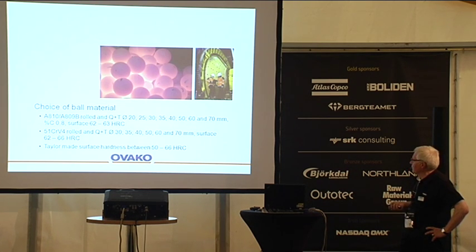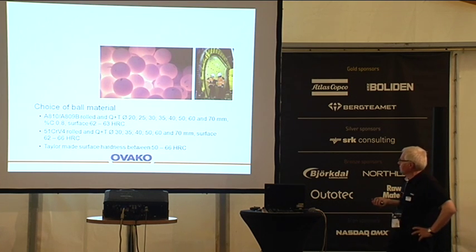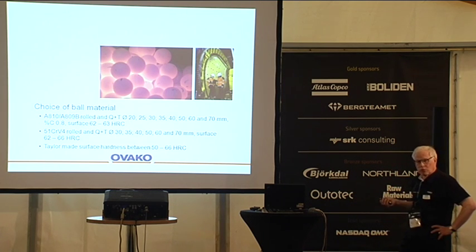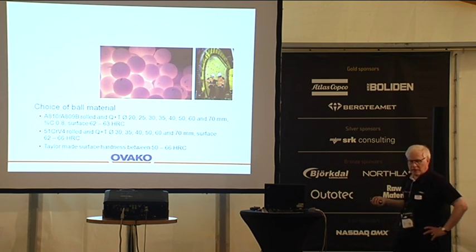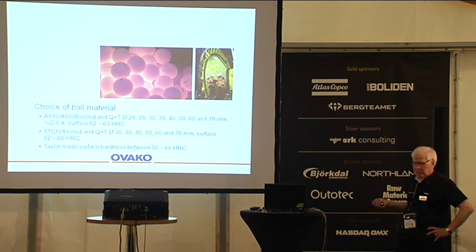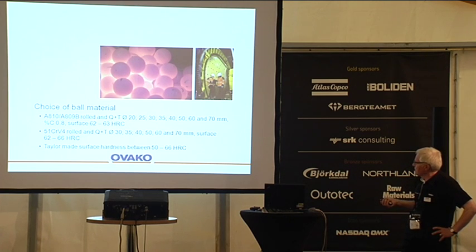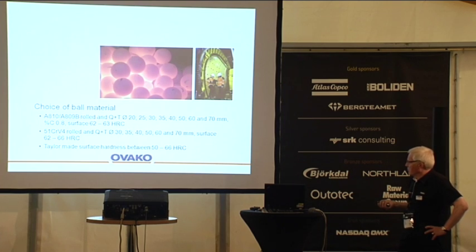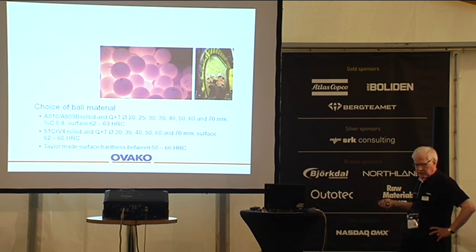For the grinding balls, we are operating since some time with two different grades. One is where we control the grain size, which is the B grade, with a carbon content of 0.8, a eutectoid kind of steel, where we can guarantee a surface hardness of around 62, 63, which is more or less also the core hardness of the grinding ball. We are also, for certain minerals, particularly in the cement industry, using the 51CrV4 grade, which can be offered in sizes from 30 millimeters up to 70 millimeters. We reach hardness levels of 62 to 66 Rockwell C, or we can define, if you have special requests on toughness, hardnesses between 50 and 66 Rockwell C.